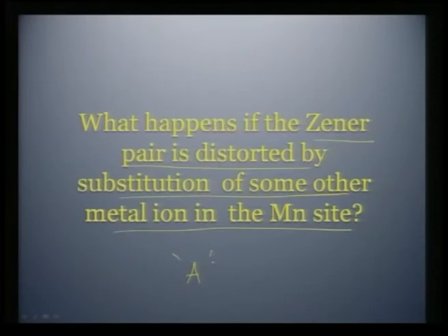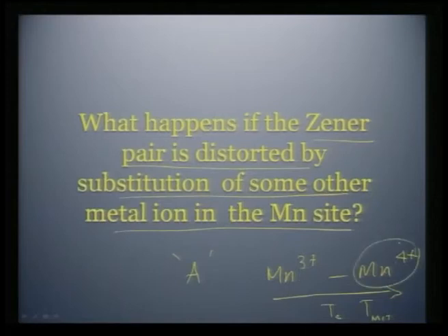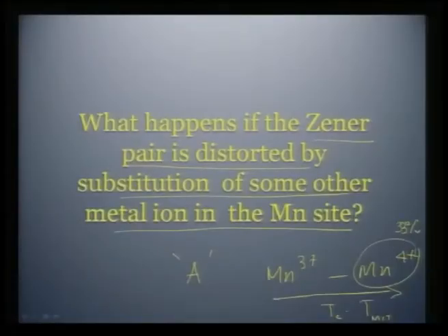As I told you, if you substitute in the A site, that is the lanthanum site, then Mn3+ goes to Mn4+, which is advantageous for us, and therefore you see a ferromagnetic ordering and a metal to insulator ordering, which is increasing as you generate more and more Mn4+, up to a critical concentration of say 33% of Mn4+. Beyond 33% of Mn4+, you do not see any net change or a spectacular change. In other words, sometimes it becomes detrimental. So, this is the optimum at which you can get a maximum TC and maximum metal to insulator transition.